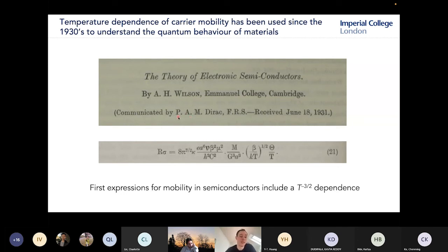In this really seminal work by A.H. Wilson in 1931, he developed expressions for charge transport in semiconductors under the assumption that lattice vibrations were the dominant source of scattering. What he found was that under these approximations, you'd expect the mobility to have a T⁻³ᐟ² temperature dependence. So as you increase the temperature, your mobility drops with this dependence.